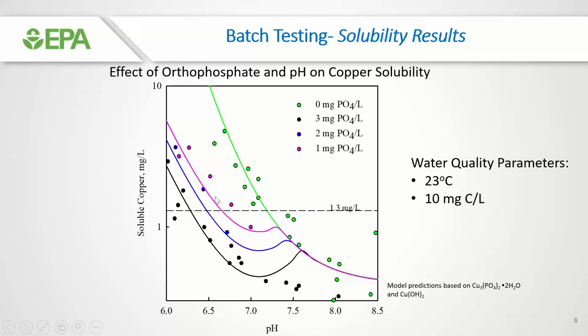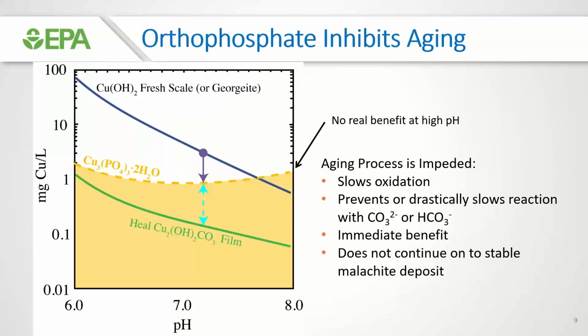Now, the theoretical line, and where things sort of fall apart, is that we don't really understand exactly what's precipitating. So theory doesn't predict this, and we continue to try to understand and study it these days because we still don't fully understand, because the material that we generally precipitate is an amorphous-based material. But nonetheless, it truly is effective. How does this work, and how does this apply to our aging model?